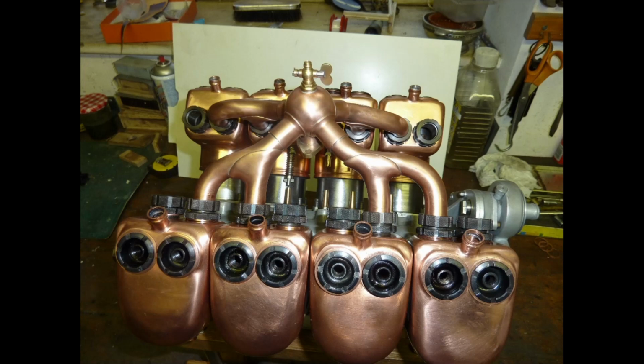The engine now has had nearly 5 hours of run time, and it's going beautifully, I must say. All 8 cylinders firing, and not much oil being spewed out, no smoke, and it runs about 2000 RPM maximum or a little more. Idles at about 900, and we did a spring balance thrust test on it some time ago and registered about 20 kilograms at 2000.